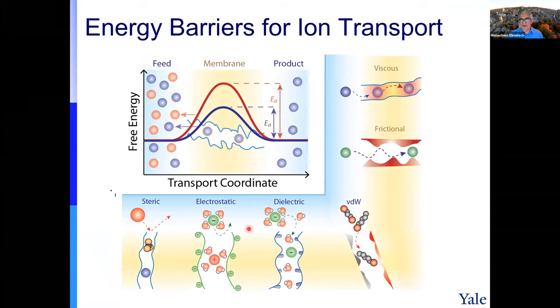Now I'd like to go over a few more slides, again showing the additional selectivity between ions for different membranes. I will show you some ion exchange membranes. Generally, it's common in this literature to describe the transport by the energy barrier for transport. In this example, we have red ions that have a high energy barrier, so they will not cross the membrane. You see no red here. And if the energy barrier is low, like the blue ions, they can go through the membrane. There are many reasons why you get this energy barrier. You can have steric, electrostatic, or dielectric effects, all described in a perspective article that I mentioned.